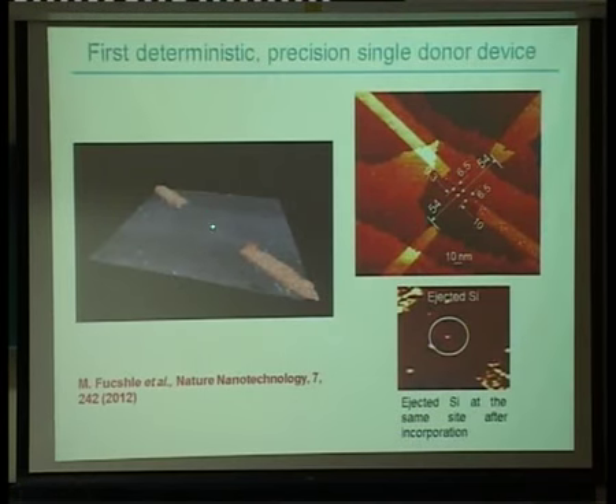That's actually the hole that we've opened up with the resist technology. And this is the actual ejected single silicon atom that's come out once the phosphorus has gone in. So with the STM, you actually image it in the whole fabrication process, so you know exactly where it is. And I guess the key thing then is you've got to get that through the clean room to put your contacts down without killing the device, which is always the hair-raising moment for the student.